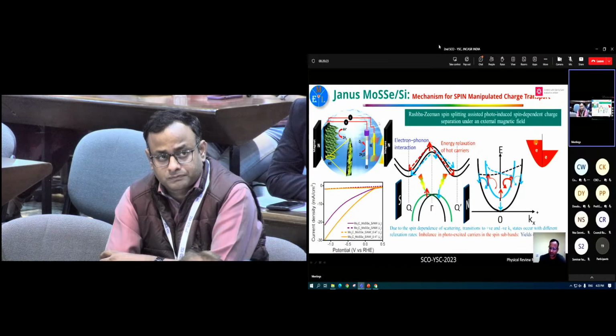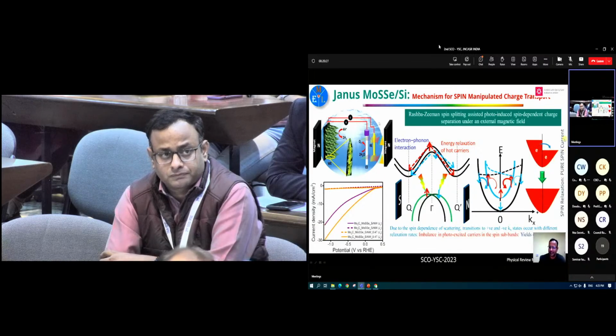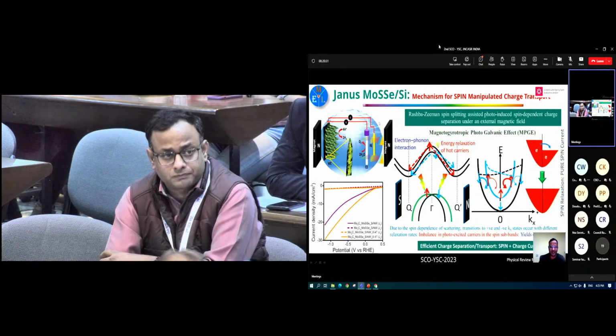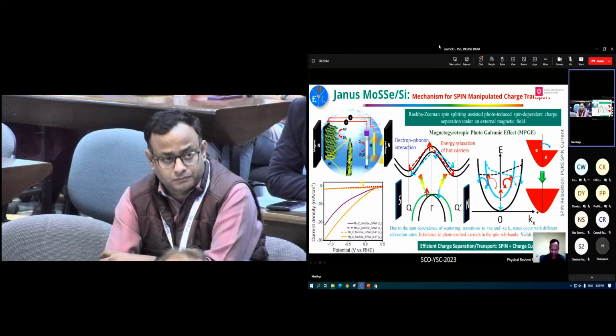So this diffuses from higher to lower density, and this is called the pure spin current. So this is where you have a spin current and the charge current, and this effect is called the magnetogyrotropic photogalvanic effect. Due to this effect, you have efficient charge separation, and the addition of the pure spin current gives us this enhancement in the photocurrent, and also higher activity in the photoelectrochemistry.